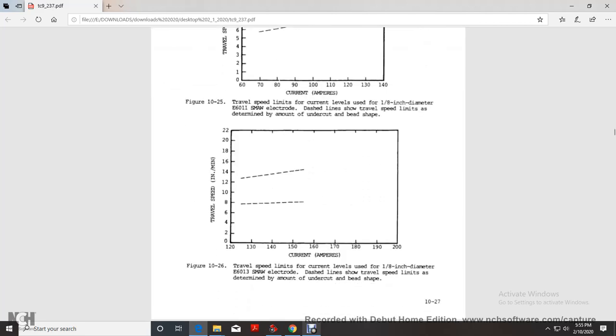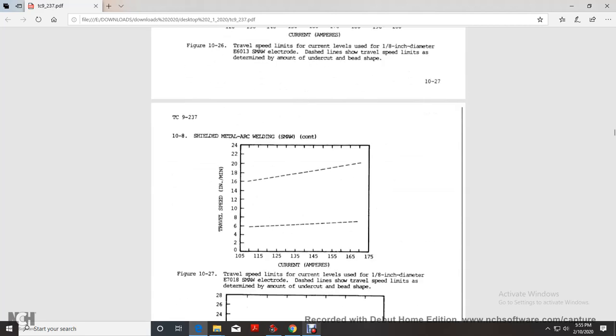And then you have the current in amperes and the travel speed in inches a minute. The travel speed limit for the current level of a 1/8 inch diameter E6013 shield metal arc weld, dash line, is limited by the determined amount of undercut and bead shape. And then Figure 10.27 shows the travel speed limit for the current level of a 1/8 inch diameter E7018, with the dash line travel speed limited by the determined amount of undercut and bead shape, current in amperes, and then travel speed.